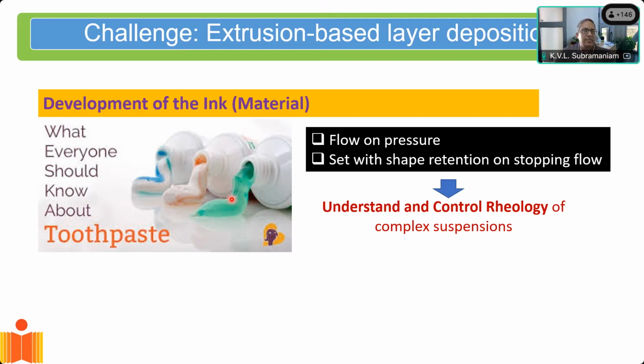So it's basically sort of like zero slump concrete, but the zero slump concrete should be able to flow. And that is where it becomes very challenging. Because we do have zero slump concretes, I'll show that to you in a minute, which are used in pavements. We use them for slip form construction, etc. But those don't flow. We basically vibrate the heck out of concrete to put it into shape. Here, I want it to flow under pressure. That is, it has to go through a pipe. So that is one of my biggest challenges, is I have to now balance both of these requirements.